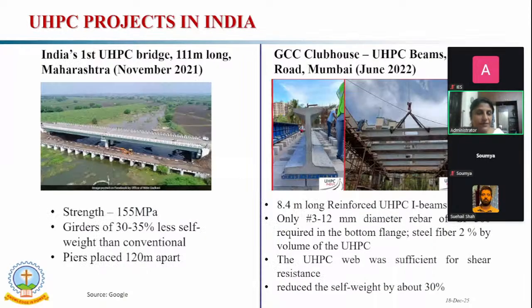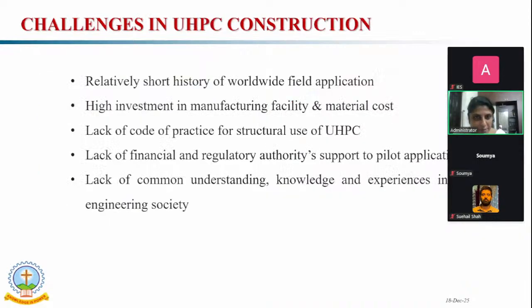Then India's first UHPC bridge is in Maharashtra. With UHPC, they could reduce the self-weight by 30 to 35% compared to conventional concrete, with a strength of 155 MPa. Then in the case of the Mumbai GCC clubhouse, it is also 8.4 long UHPFRC. They have considered only 3 to 12 mm diameter rebar. In that case also, the self-weight could be reduced by about 30%.